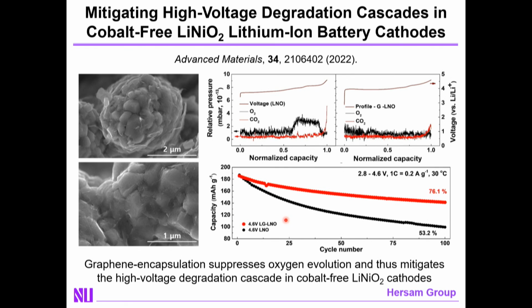For completeness, I will note that this approach is one that works not only on conventional cathode materials like lithium nickel manganese cobalt oxide, but can also enable next generation cathode materials such as lithium nickel oxide. Lithium nickel oxide has not made it commercially yet because it has an issue. In particular, at high states of charge, the oxygen becomes unstable and is liberated from the cathode. This is so-called oxygen evolution.